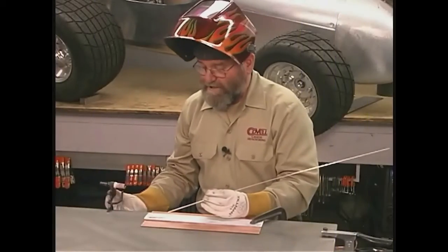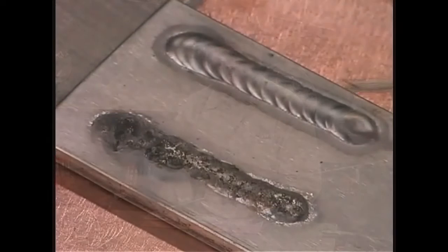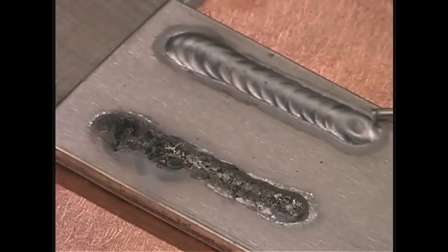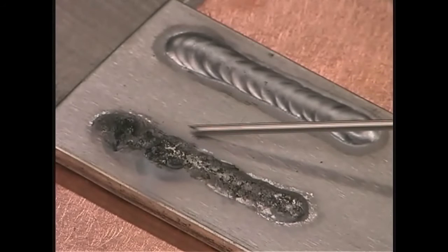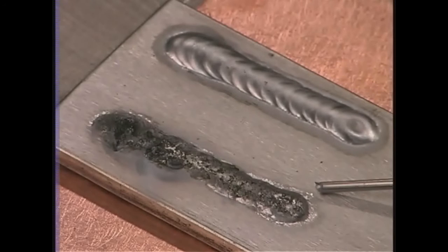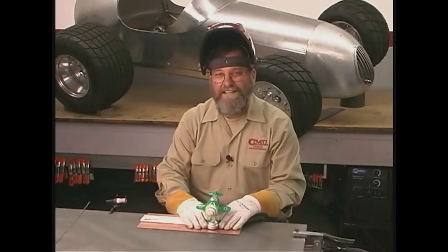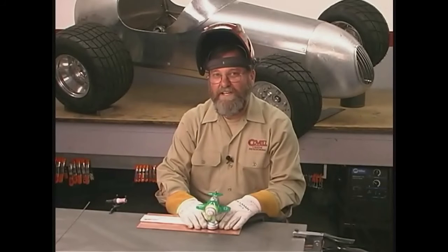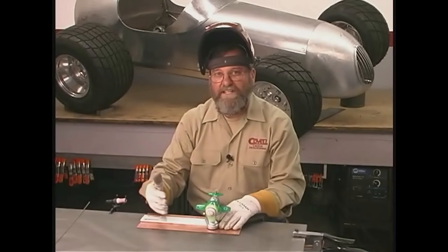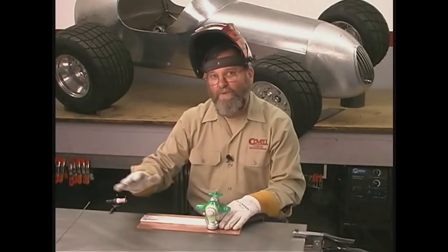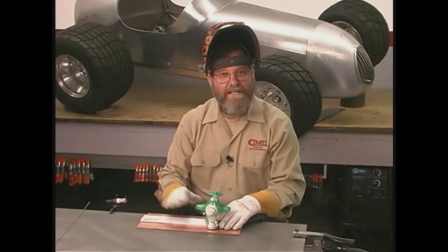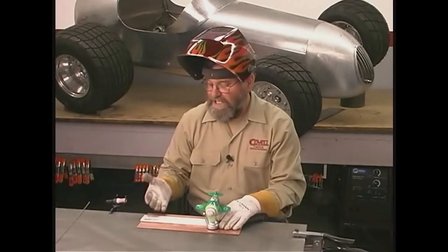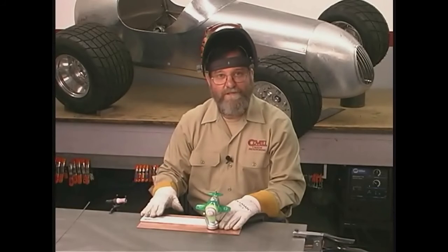So let's take a nice close look at these two welds. So the weld made with enough argon flow is clean and shiny. The weld made with not enough argon flow is really, really dirty. This is something I had to learn the hard way. Even a tiny breeze will be enough to blow away the shielding argon gas, and you'll get contamination in the weld, just like the case where we didn't have enough flowing.